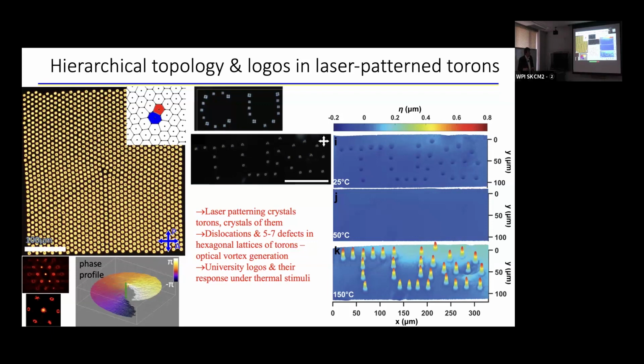And then as we would polymerize it, in this case at 50 degrees Celsius, right? That film within which we have these solitons is flat. The color in here is showing surface topography. But now, interestingly, as we cool it down to room temperature, we got the array of holes that reproduces the topology we have within it. So for every single toron, we have a hole in that place.